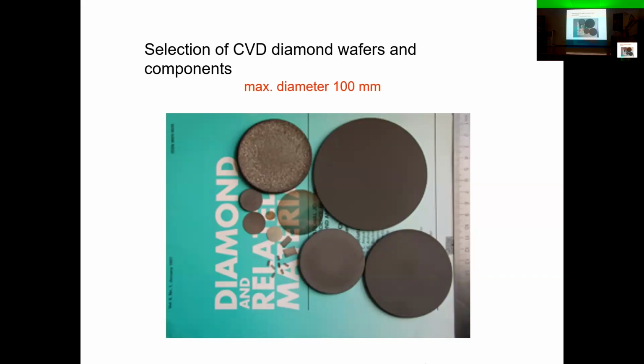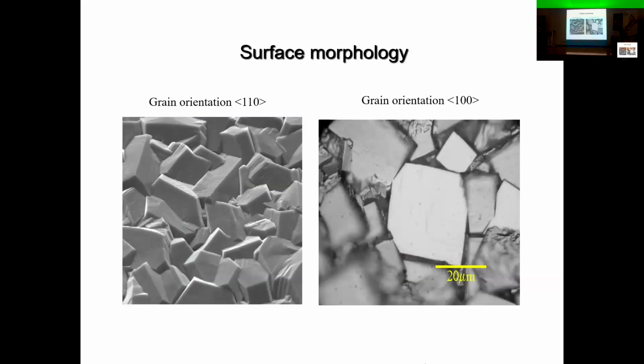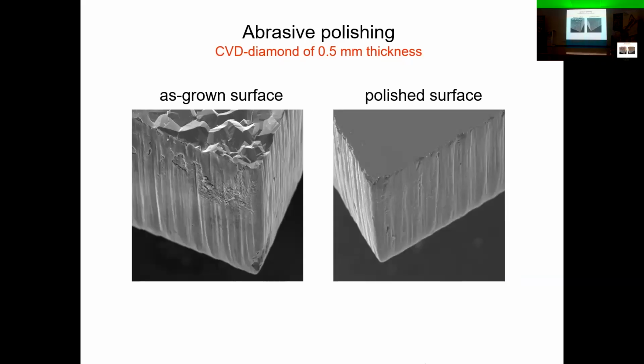They are different diamonds. You have seen several slides before. This one has good optical properties. This is good for other applications. This is probably with addition of nitrogen, so it's not so transparent, but for many applications it is interesting. This is an example of surface morphology of this polycrystalline diamond material. So crystals are of sizes of micrometers, which makes the properties of this plate very good. So it has very high, for instance, thermal conductivity. This is a polished surface of diamond.